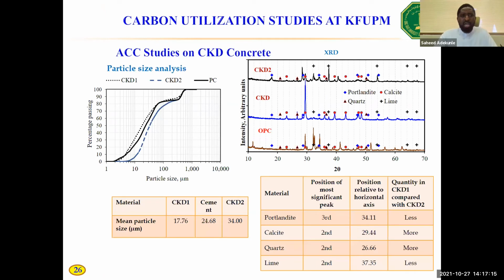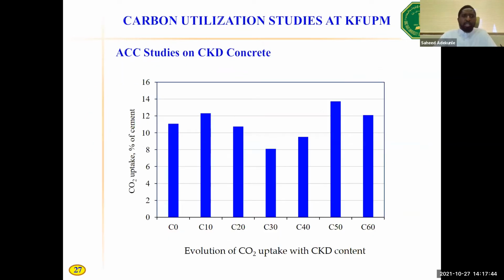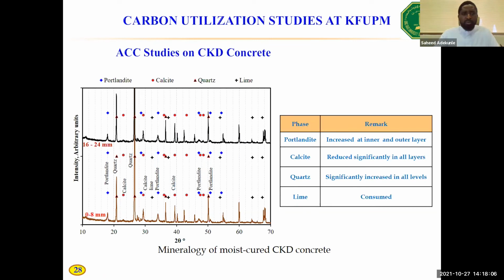Now, from this research, we were able to use two different CKDs. And as you can see on the screen, CKD itself has a lot of calcite and a lot of lime. The lime content of CKD is our target in this material, just to enhance the CO2 capture ability of our concrete. And the result is that in this research, we're able to raise the bar from 7% by mass of dry cement to as high as 14% by mass of cement by simply incorporating this waste material called CKD. And I don't want to go into technical details of this particular research work.